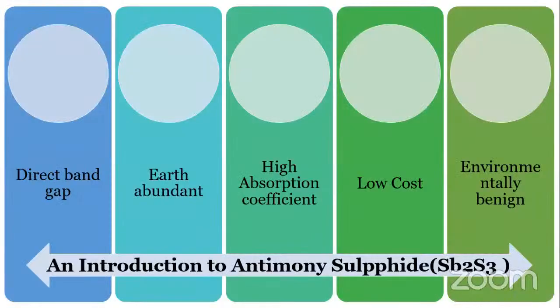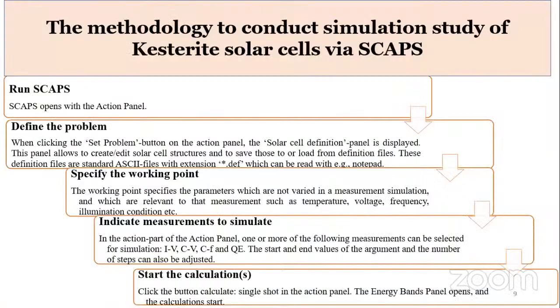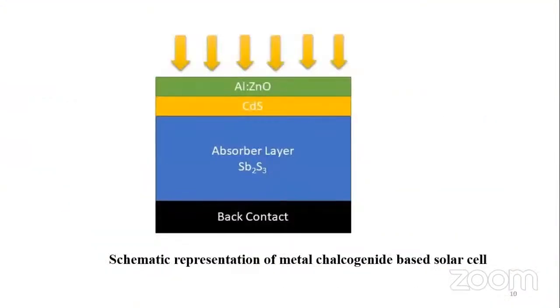Since we are talking about metal chalcogenide solar cells, we have used antimony sulfide, Sb2S3, solar cells. It has a direct band gap. It is abundant. It has a very high absorption coefficient. It has low cost, and it's an environmentally benign material. This is the structure which we have simulated for solar cells.